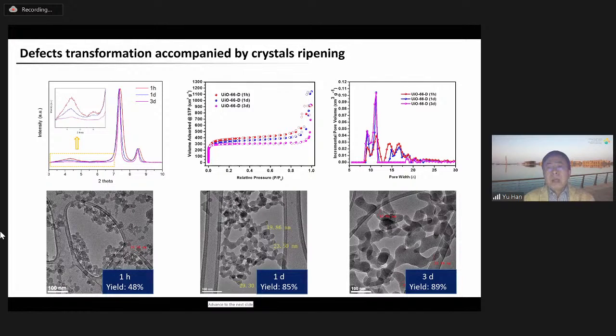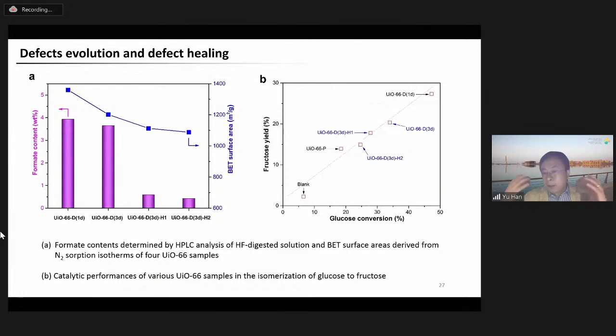HRTEM. Knowing this evolution of the defective structure, we can prepare a number of UiO-66 samples with different defect types and concentrations, just by tuning the crystallization time and combining with the so-called defect healing method. And then we got a number of samples with different degrees of defects. We use these samples as Lewis acid catalyst for the isomerization of glucose to fructose, and we found a clear correlation between the catalytic activities and the degree of the structure defects.